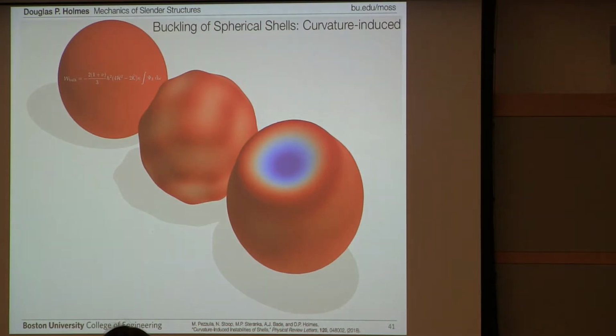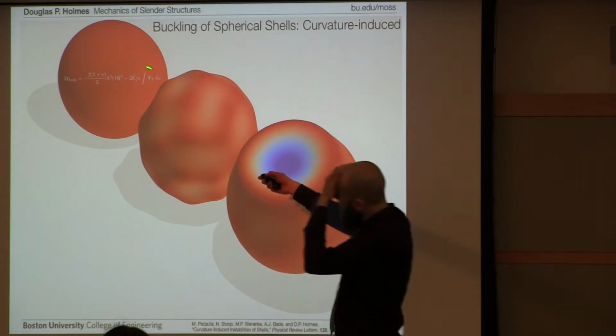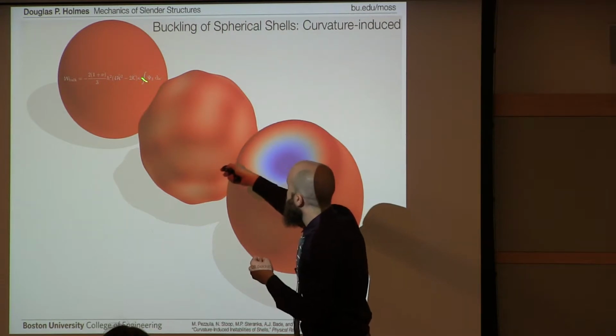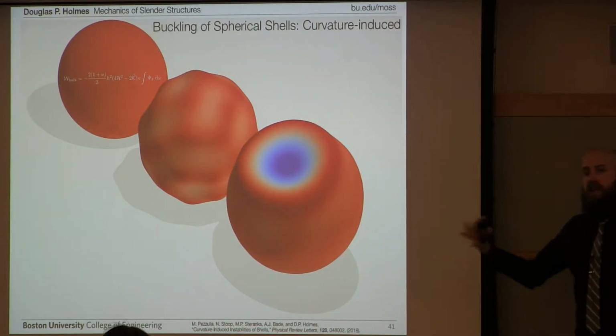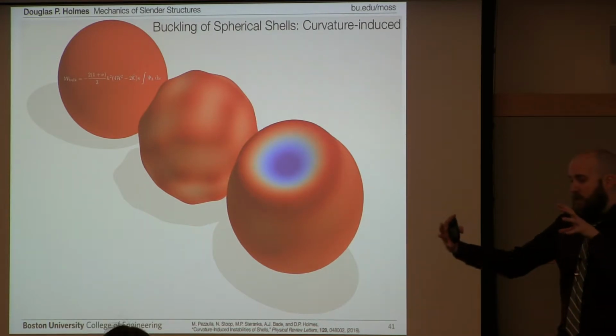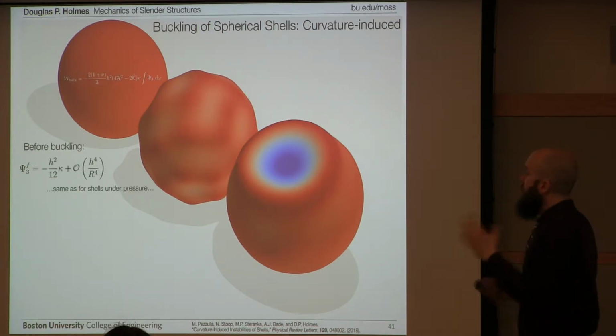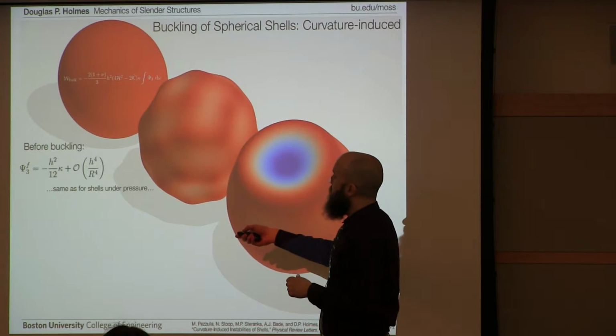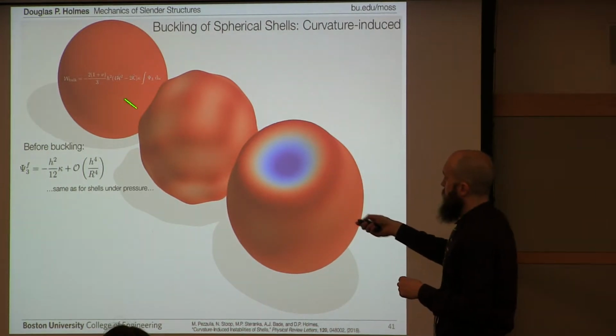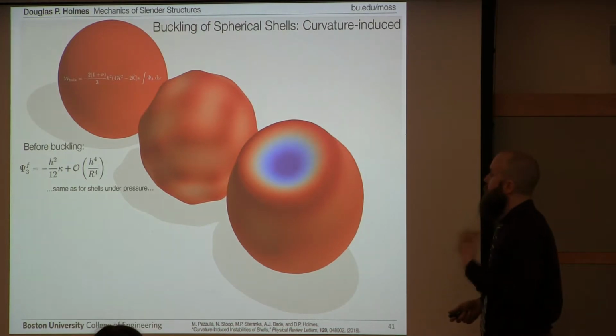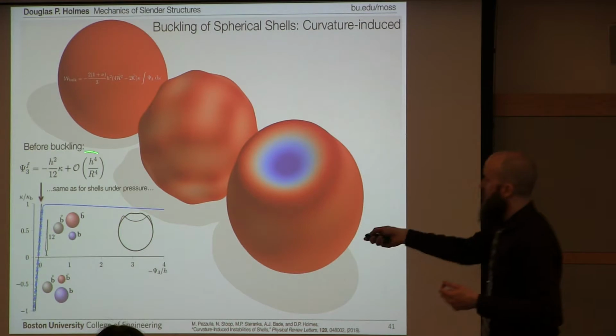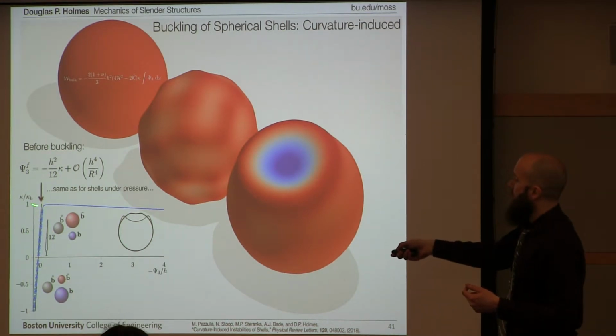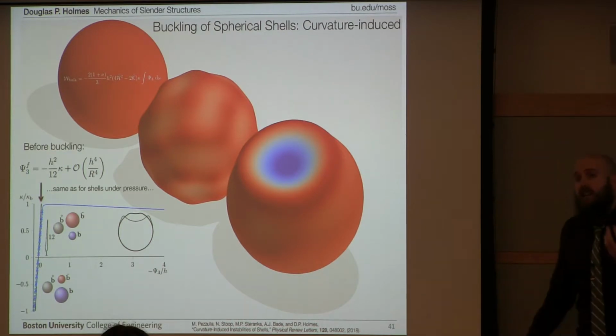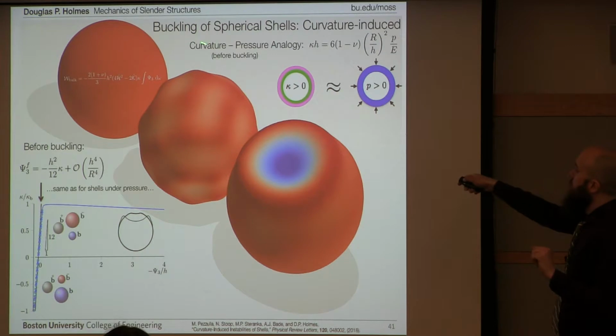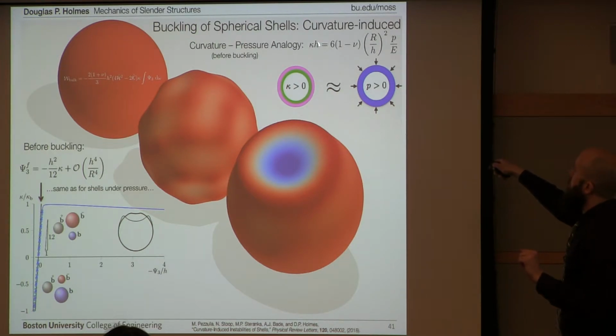So can we understand this buckling process by looking at this term here? And if you study shell mechanics, you would know that this term that's in this integral here is exactly identical to what you find when you have pressure acting on a spherical shell. The pressure acts to normally displace this shell. And this is great because now you can, for instance, say before buckling, the behavior of these spherical shells under curvature stimuli is exactly the same as the behavior of spherical shells under pressure stimuli. And so you can confirm this here with a graph that shows that the displacement of the shell completely matches what you would find from pressure. This is nice because it allows you to connect these two seemingly different things, pressure and curvature, with this analogy that as your curvature goes up, it's kind of analogous to the pressure of your shell going up.